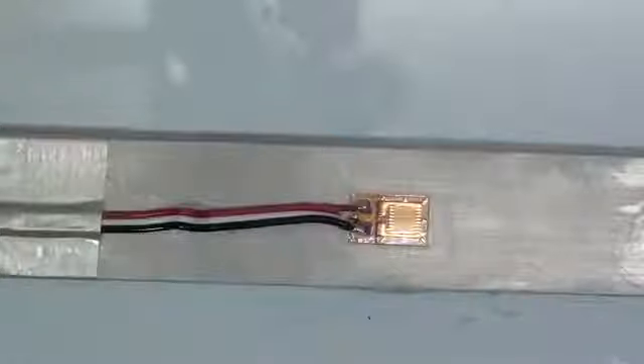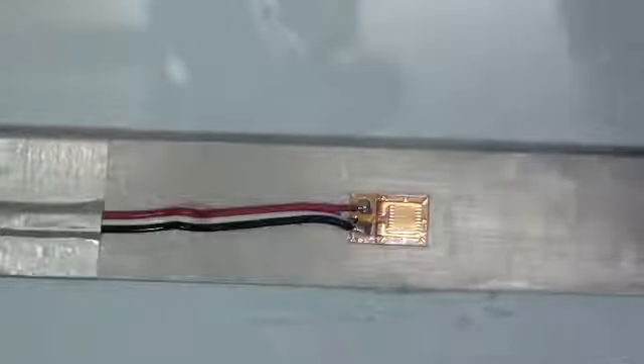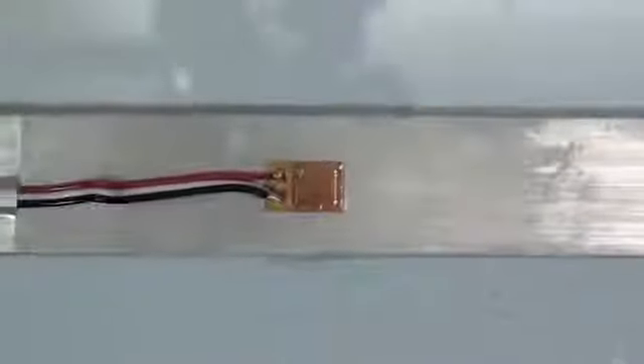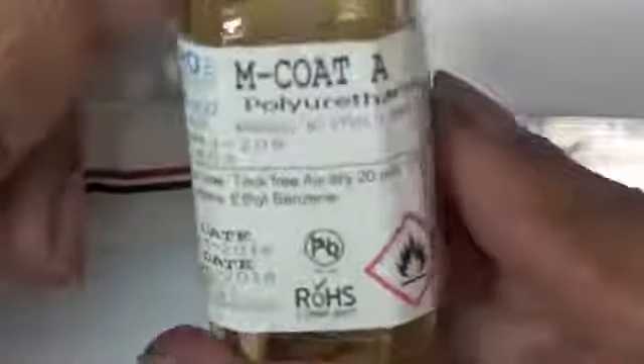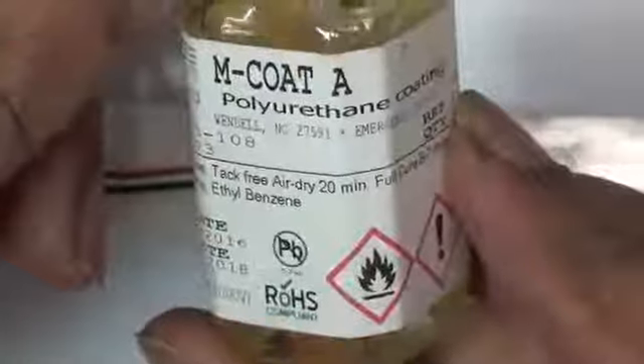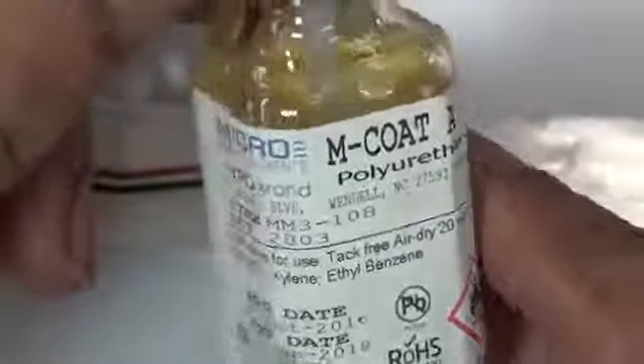Okay, so now we're ready to apply a protective coating. The coating that we're going to use in this application is Micromeasurements M-Coat A. This is an air drying polyurethane coating. And this is mainly used for lab applications. You would probably not want to use this coating. You'd want to use a different coating if this were going to be an outdoor application or on a component that was subject to some sort of chemical exposure. We have coatings that work for that.